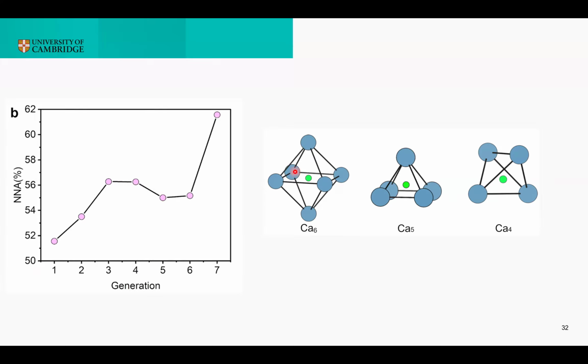But how? What happens is that the non-nuclear attractor, this characteristic of the electride, here represented by this green dot, is always found inside metallic clusters, in this case of calcium, the blue spheres. And this is similar to what was observed in other electrides, like in sodium or magnesium, in the cases that I showed before. Therefore, there is a direct structure-to-property relationship between the formation of calcium clusters in this type of compound and the appearance of non-nuclear attractors. As a consequence, the crystal structure prediction basically promotes those structures that are characterized by the calcium clusters, which then results in an acceleration of the generation and discovery of new electrides.